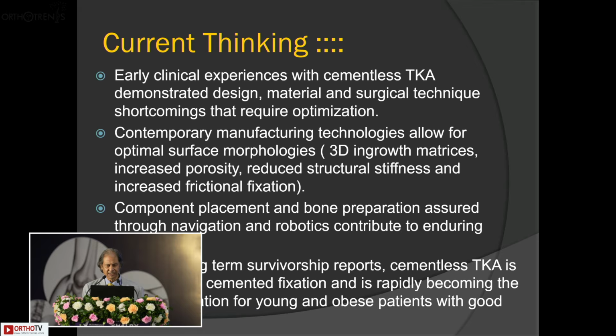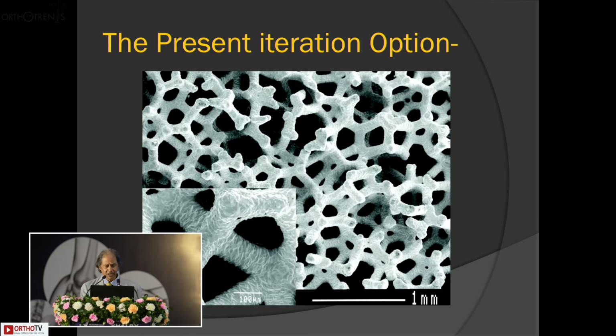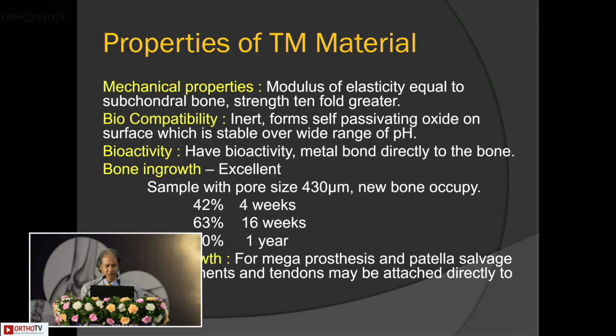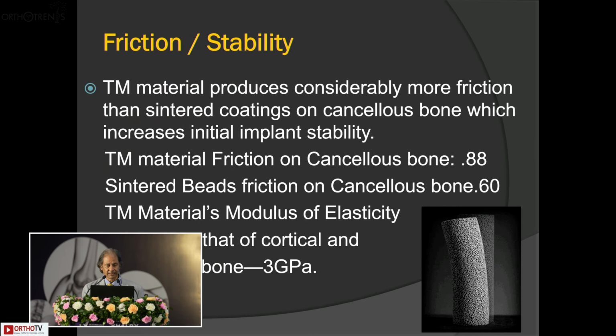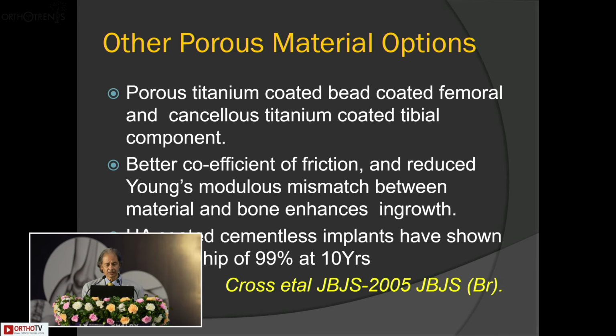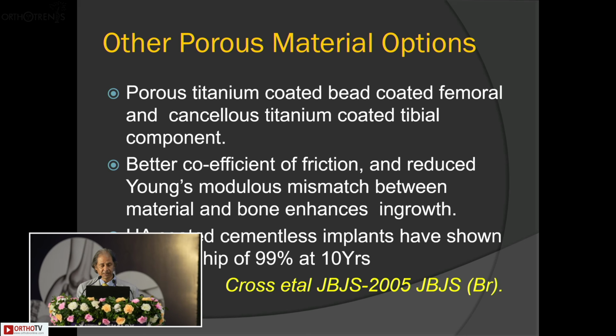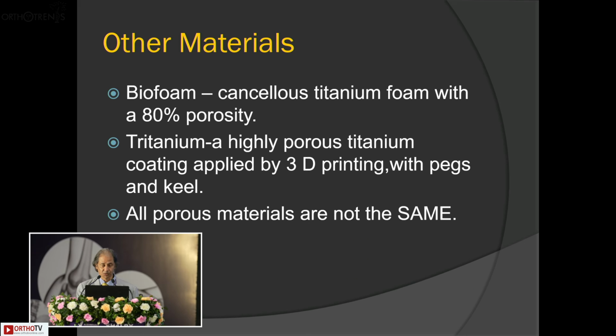We have experience of the TM type of cementless options, and this is the macro reticular pattern of the TM profile. So these are biocompatible, bioactive, have a coefficient of friction between cancellous and cortical bone, and really attach very well, with a coefficient of friction which is very similar to cancellous bone. So these are other porous materials like porous titanium, which again have a high coefficient of friction, and HA coated implants have shown survivorship of 99% at 10 years, which is really quite excellent.